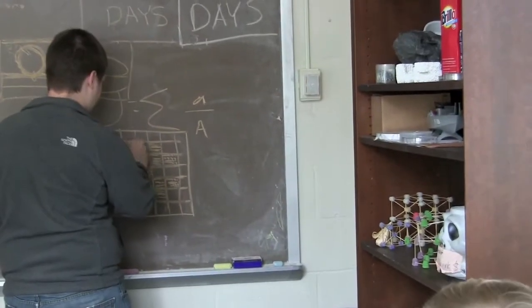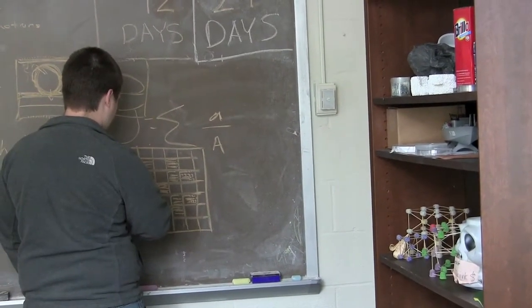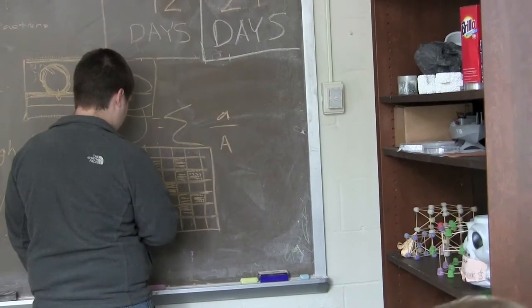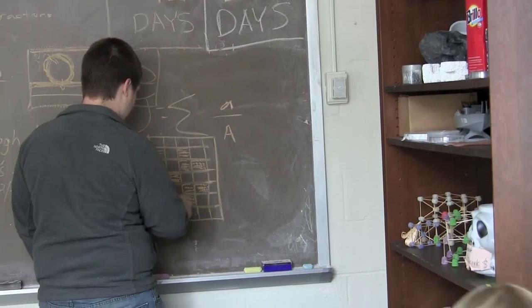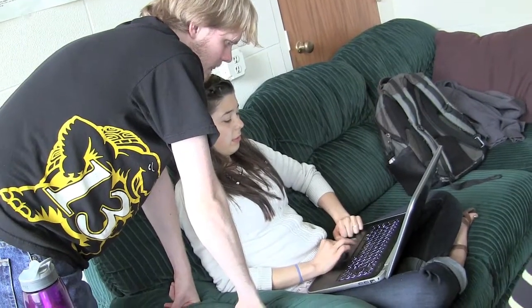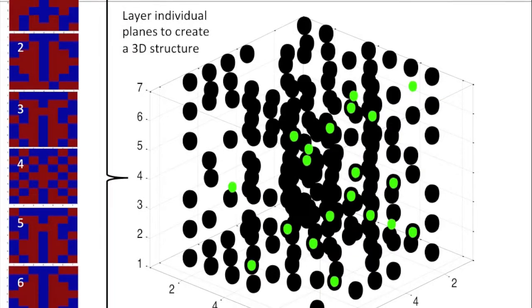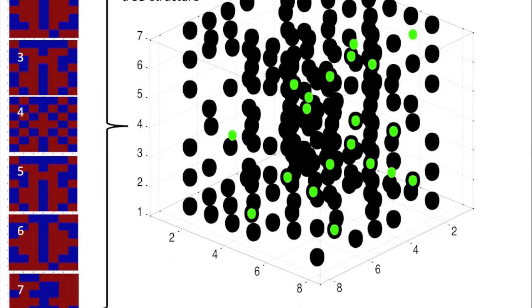We wanted to have a good understanding of how dendrimers were actually acting in solution, so we decided to make a computer simulation in MATLAB. The system we used was the bulk solution, the dissolved chlorine ions, the dendrimer monolayer, and the titanium oxide. Altogether, it was modeled by creating a 3D matrix with filled sites acting as either chlorine ions or densely branched dendrimer areas.